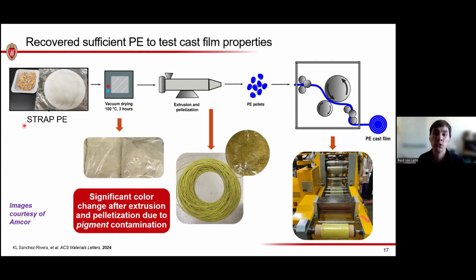And so here's the first challenge where contamination plays a real role. Here's the polyethylene that we recovered from that solvent-based process. We dry it out. You'll notice that it looks very nice and white, exactly how we want it to be. We send it through an extruder, so basically we make it into this rope-like material that is then what's used to produce the final film. And you can see a color change, and that color change persists into the production of this film at Amcor. So this is really the material. Now, this color change is a really big issue. We can't sell this because it clearly has a property that isn't as good as the virgin material. We did a lot of work to show that this was the result of contamination.